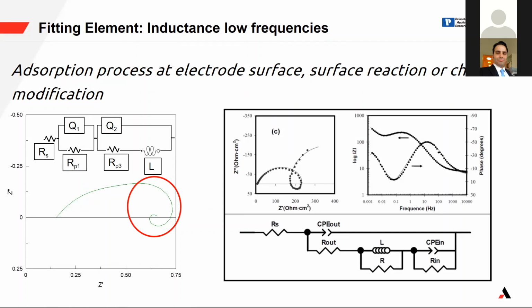So you see the inductance is here. And this one is not a problem of wrong frequency range. This is part of your measurement. So what happened? You have an adsorption process at the electrode surface, and you have a surface reaction or a chemical modification of a reaction. So the system, you start with something, and after the measurements, this something changes. The resistance of this something in your cell changes. So in this case, I have this modification, or I have that very nice circle on the system, so I have an inductance in the middle or at the end of my experiment.